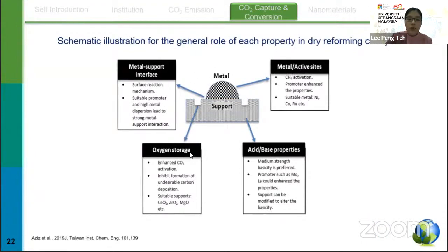This scheme shows you how we are going to design a very good dry reforming catalyst. For a dry reforming catalyst, you have metals which act as the active site, and also the support. Between the metal and the support, there is a metal-support interface, and it is at this interface that the surface reaction mechanism occurs. That is why we need a very suitable promoter and also high metal dispersion that lead to strong metal-support interaction to enhance the DRM process.